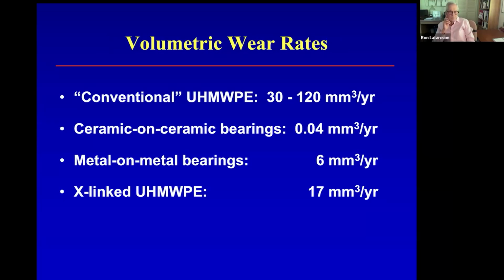So the volumetric wear rates that we're talking about are for the conventional polyethylene that was in the late 80s and early 90s. It was a volumetric wear rate of about 100 cubic millimeters of polyethylene per year. And the competing technologies introduced at that time to reduce that wear rate were ceramic on ceramic bearings, metal on metal bearings, and also highly cross-linked ultra-high molecular weight polyethylene, where there was purposeful cross-linking with electron beam or X radiation, and then subsequent annealing or quenching to remove the free radicals.